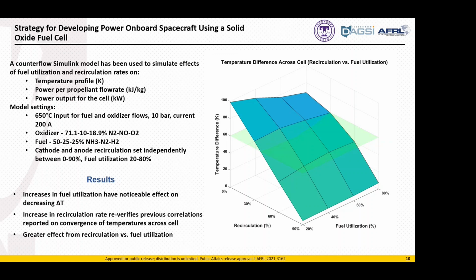Yeah, well, our proposal currently is that you would have basically a heat exchanger setup here, and again, I don't have release on this, but using the exothermicity of, say, the hydrazine decomposition, we can heat up the NTO flow as well, up to a temperature at which the NO2 decomposes as well. Through our own kinetic analysis, I used a Monte Carlo solver, and looking at literature as well, some of the old NASA reports, Aerojet Rocketdyne, we are going to have some remainder of NO at the SOFC temperatures. Some remainder of nitric oxide in the cathode stream. That's what I had seen.